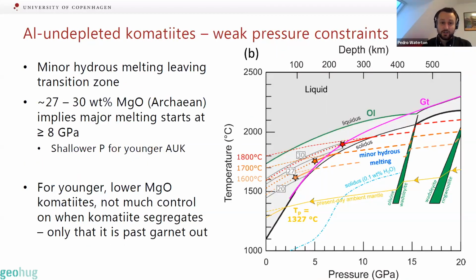For aluminium undepleted komatiites, we don't have such good pressure constraints. These kinds of komatiites are generally the ones where a bit of water has been found in the melt inclusions. And so what this means is that pretty much regardless of the temperature, as you leave the transition zone and cross the wadsleyite-olivine transition, you'll get a little bit of minor hydrous melting. And we're not really sure what would happen with these melts. Maybe they escape upwards, maybe they get incorporated later, or maybe this melting isn't enough to fully dehydrate the komatiite and you retain a bit of water that is then what we're measuring at the surface.